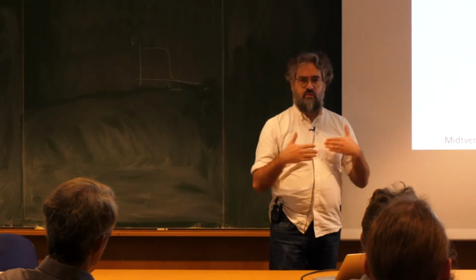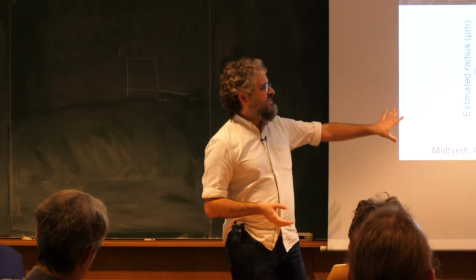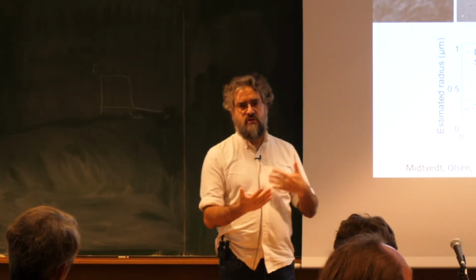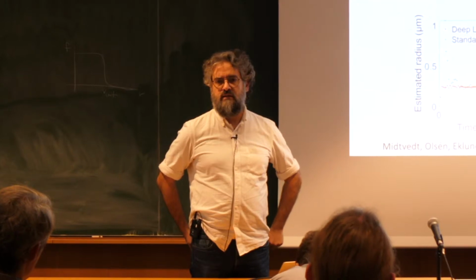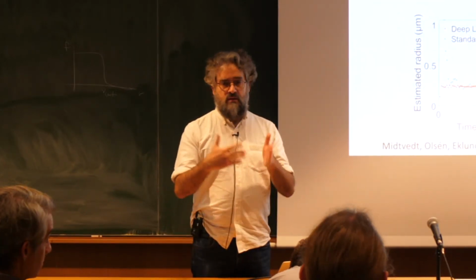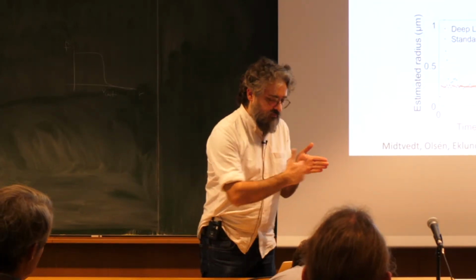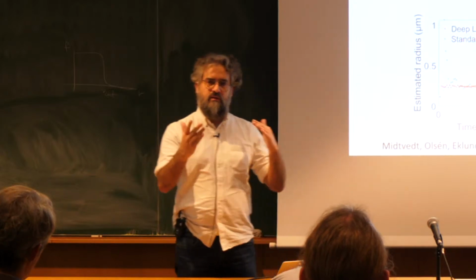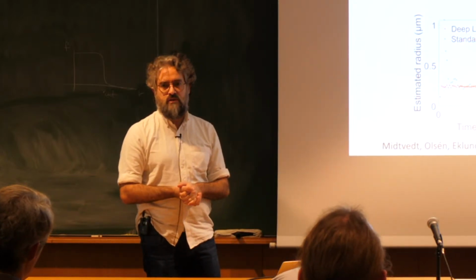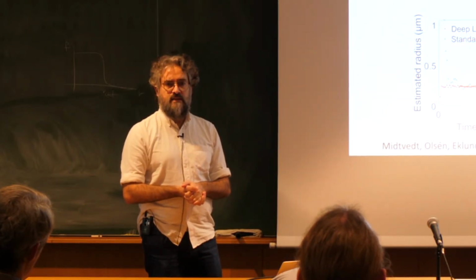No, we simulate over a broad range of radii. This is just one plot. We also have a plot where we show that we can distinguish particles that are 100 and 200 nanometers with the same radius, same network. So you generate a large set, and you can train over a very big range of radii and refractive indices.